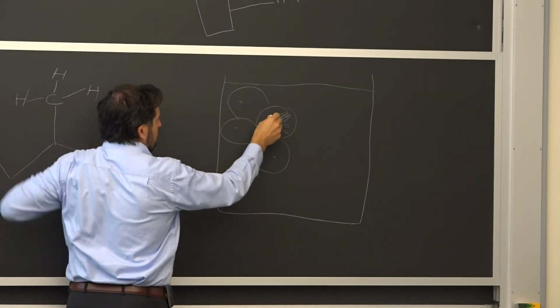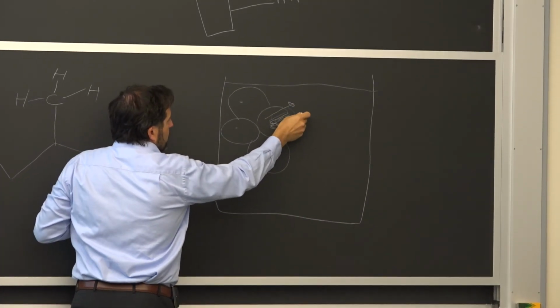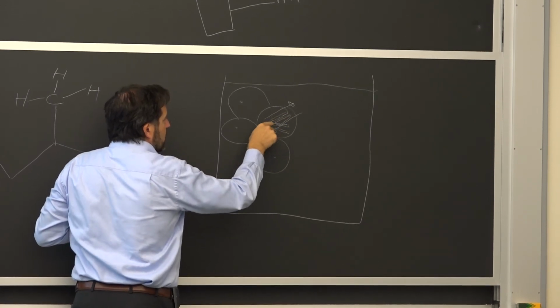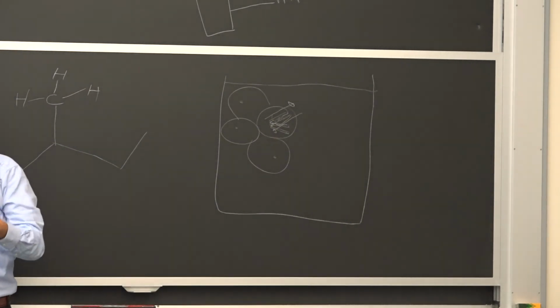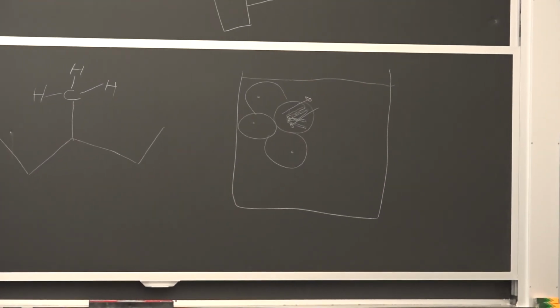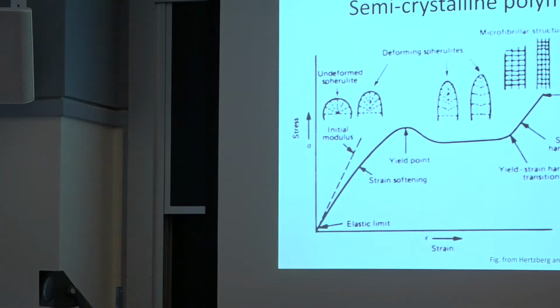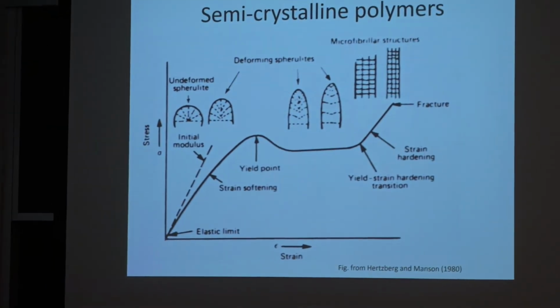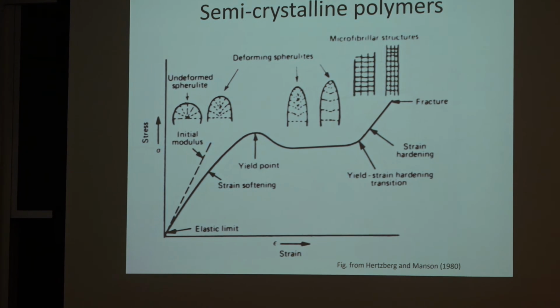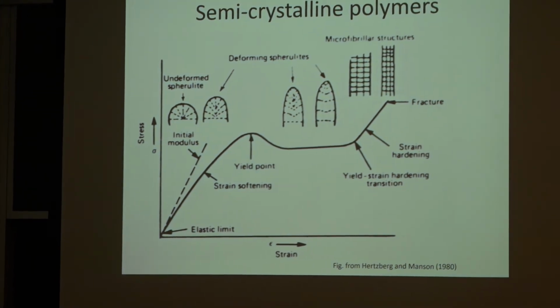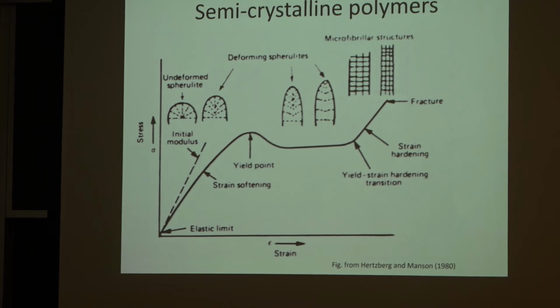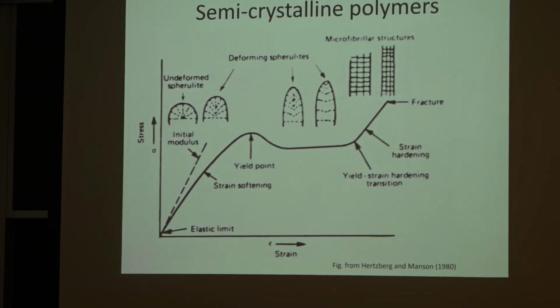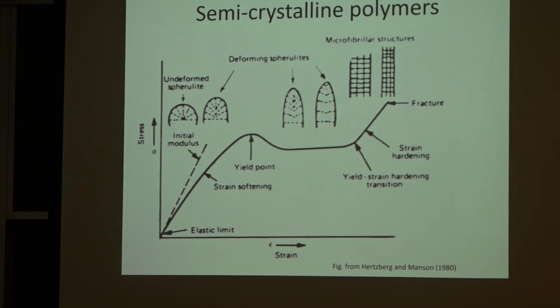So here, if I'm thinking about pulling this way on something that's been compression molded, I'll be able to shear and essentially get my deformation to take place in the softer zone. And therefore I get deformation easily. So that's what happens at the beginning of yielding. What you see in this schematic is stress and strain over time as you keep pulling on the material. You go from spheres to something elongated. Eventually, all those crystals that we've talked about get reoriented, and now you have a composite that is reinforced.